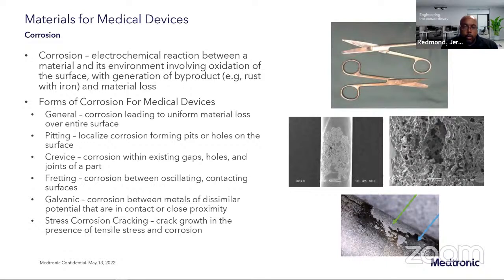And there are a number of different forms of corrosion. And this becomes very important for reusable instruments, but it also can impact implantable materials as well. If we look across that list of possible corrosion, the areas that we probably struggle with the most with implantable materials as well as instruments is around localized corrosion, such as pitting and crevice corrosion, where you can get either surface disruptions in the passive layer that forms on these metals or evidence of corrosion reactions around grain boundaries on the surface. That can result in pits on the surface.